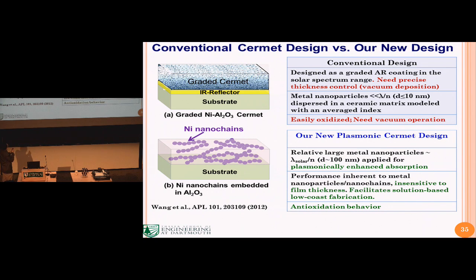On the other hand, you want to maintain the high reflectance in the infrared regime. However, in this case, you need very precise thickness control, so it usually requires vacuum deposition. And the metal nanoparticles used in this case are very tiny, typically less than 10 nanometer diameter, so they're very easy to oxidize.